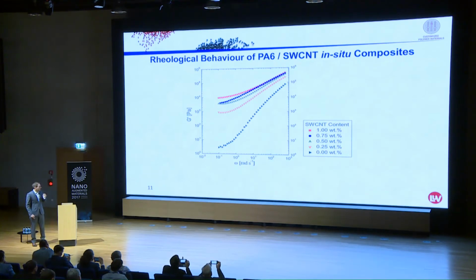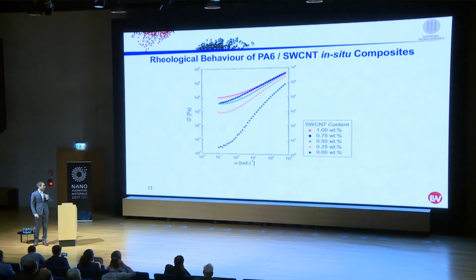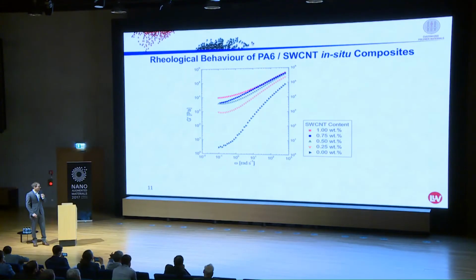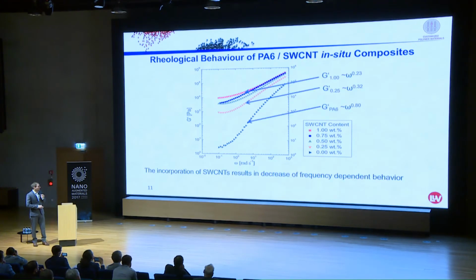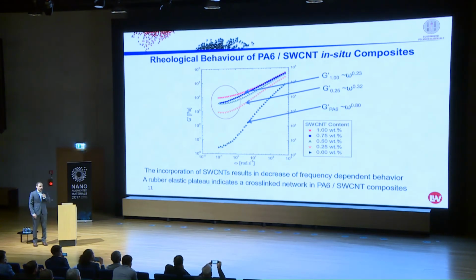So let's have a look at the rheological behavior of the material. These are results from a dynamic oscillation experiment where a mechanical frequency is applied to the molten polymer, and we see in black it's neat PA6, and then we have an increasing filler content. We see that the slope of these curves is decreasing with increasing filler content, and we also see a rubber elastic plateau at the low oscillation frequency. This is an indication for a cross-linked network, and this is pretty nice because we just saw the network. We have an optical proof of percolation here, and it's perfectly matching with this theoretical experiment.